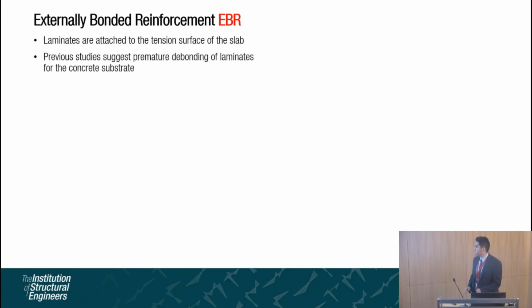There have been some previous studies in this regard, but there is a major concern with external strengthening with FRP. The premature bond failure of FRP from the substrate, which is the concrete, is one of the major issues. Before reaching its maximum level, when it reaches a load of up to 70 to 80% of its maximum allowable capacity, it debonds from the surface of the concrete. So that was one of the main concerns of this research that we have addressed. In order to address this issue, we have introduced something that's called transverse anchorages.